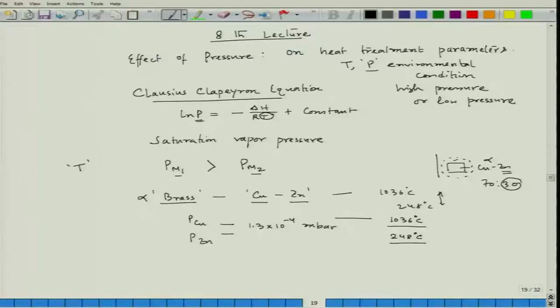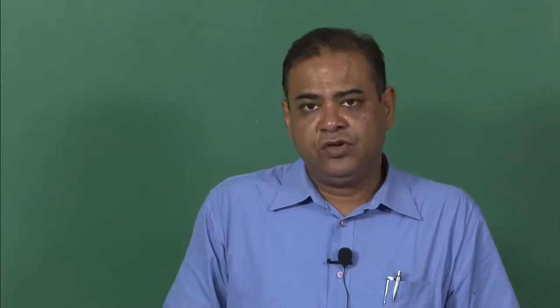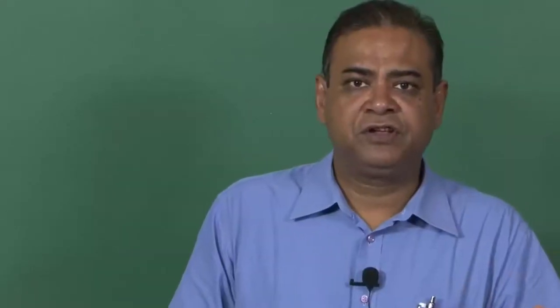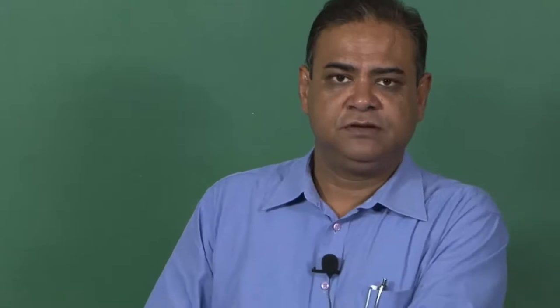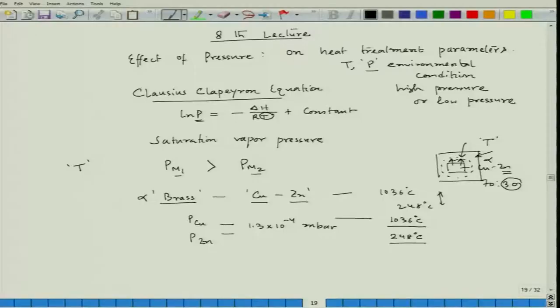Instead, we have to look into the environmental conditions. If the chamber already contains some gas molecules, whenever a zinc atom tries to escape from the surface of the solid alloy, it collides with those existing gas molecules. This collision reduces the tendency of zinc atom to form vapor — zinc evaporation can be controlled or decreased. So we need to perform heat treatment at slightly higher pressure by increasing the chamber pressure.